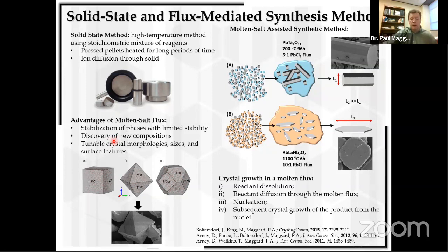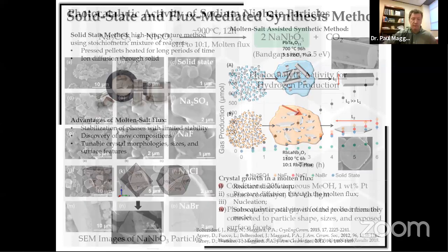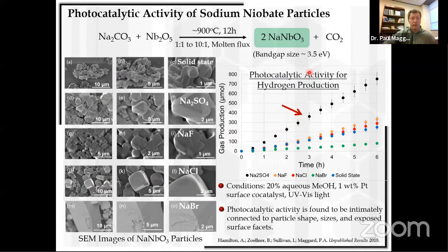depending upon their concentration within the flux, as well as the type of flux. You can change their sizes, you can change their morphologies. And so this is a very suitable, very appropriate technique to then look at how the photocatalytic efficiency for water splitting changes when you make them with different particle sizes and morphologies. And so that's, for example, one of the things that my group does.